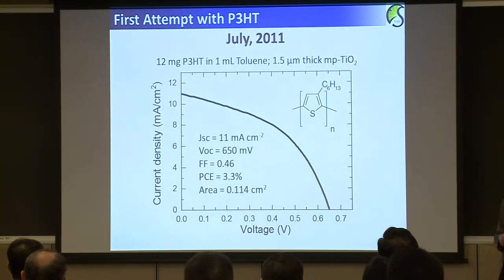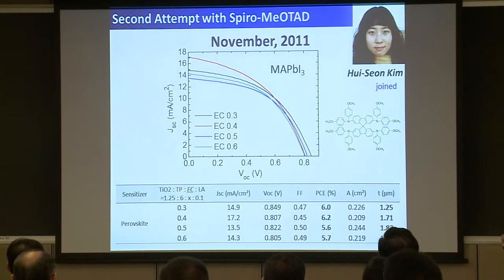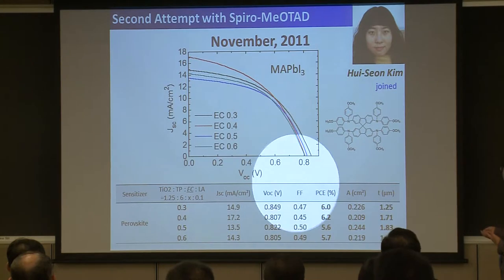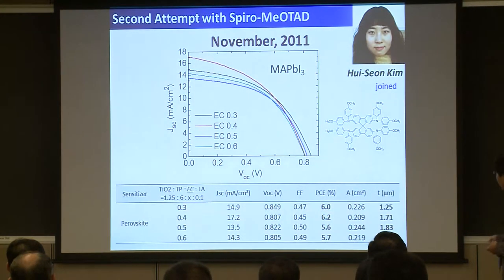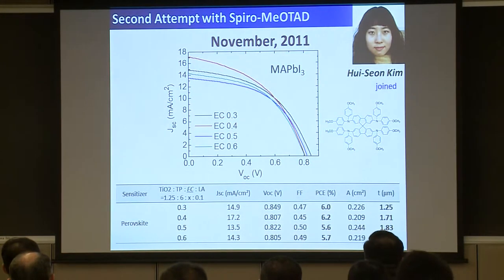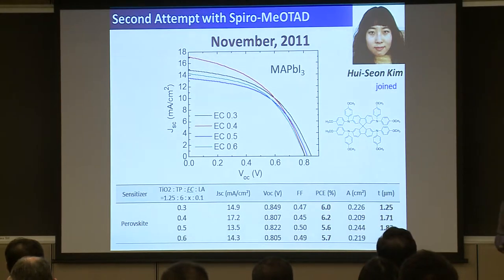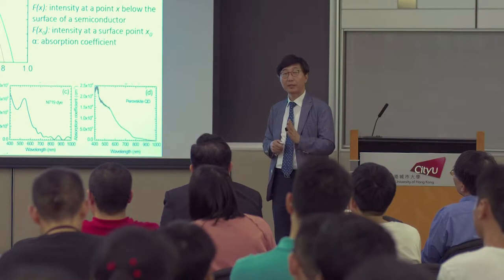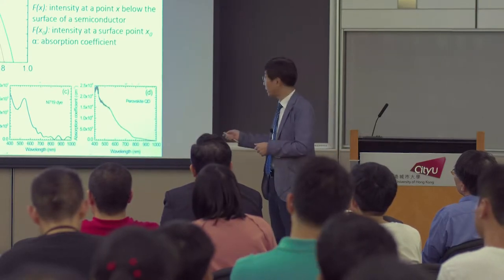First, we tried P3HT, which is well known for organic photovoltaics. But we could not get high efficiency because of the polymer nature. So we switched to a molecular hole transporting material, which is also well known. The spiro compound is a well-known material, this one. And then we could not get high efficiency. It's around 6%. Even increasing the film thickness from 1.2 to 1.8 micrometer, we could not improve the efficiency. Hui-Seon Kim, who now also has her PhD degree and works as a postdoc with Anders Hagfeldt at EPFL Switzerland, immediately recognized that our perovskite has a high absorption coefficient, 10 times higher than the conventional N719 dye.